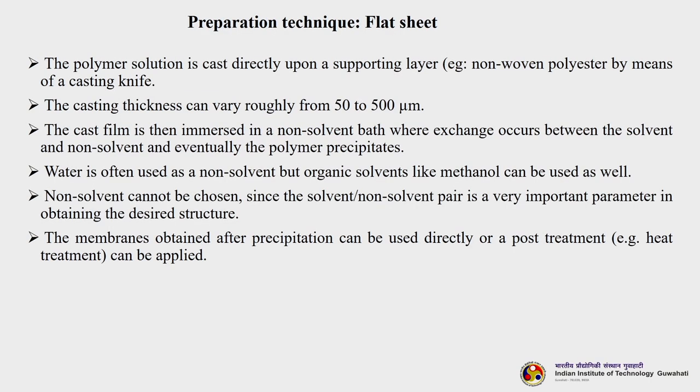So, the polymer solution is cast directly on a supporting layer, and a casting knife will help in deciding the thickness of the membrane. The casting thickness can roughly vary from 50 to 500 micron. The cast film is then immersed in a non-solvent bath.